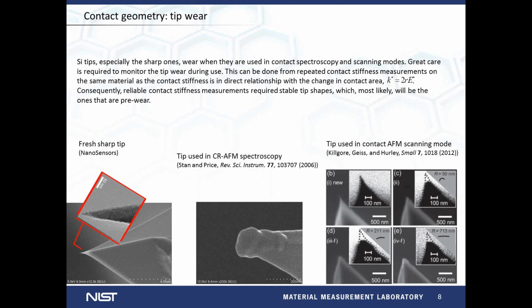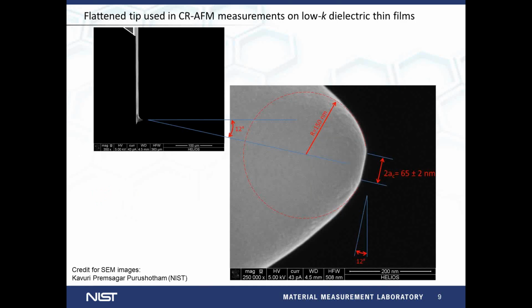But another way to look at the problem is to take advantage of this and work with a pre-worn tip shape. Here is shown an intentionally flattened AFM tip that was used in contact resonance AFM measurements on a series of low-k dielectric thin films. The tip was pre-flattened on a silicon surface at loads higher than any loads used in subsequent measurements.